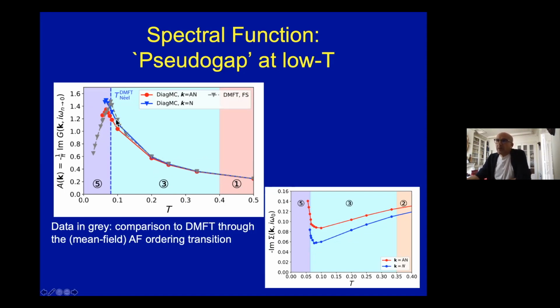And you see, by the way, that if you simulate this problem with the magnetic phase DMFT, the ordered DMFT doesn't do such a bad job following this behavior. Correspondingly, when you reach the insulating pseudogap regime, the scattering rate at both the nodes and antinodes, but at slightly different temperature scales, explodes and becomes very large.